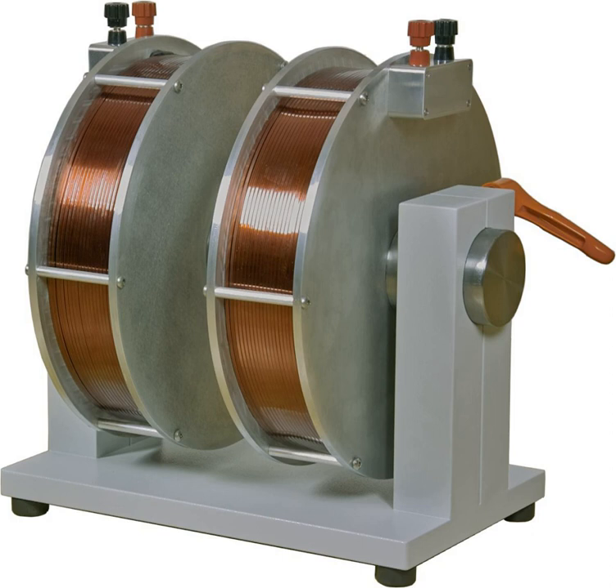However, if the magnetomotive force is well above saturation, so the core material is in saturation, the magnetic field will be approximately the saturation value B_SAT for the material, and won't vary much with changes in NI. For a closed magnetic circuit, no air gap, most core materials saturate at a magnetomotive force of roughly 800 ampere turns per meter of flux path.